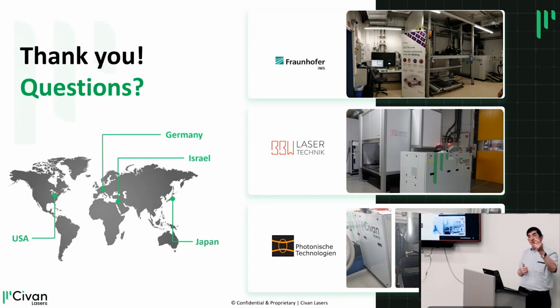And then if you have thicker material or thinner material or material with better thermal conductivity or worse thermal conductivity, you have to adjust the power to the process. So let's say if you weld mild steel of a few millimeters, you use, I don't know, 3 kilowatts. The same thing for aluminum is going to require 6 kilowatts, and the same thing for copper is going to require 9 kilowatts. So it definitely depends on the properties of the metal.